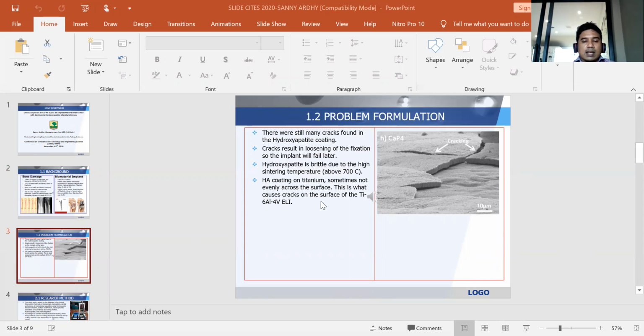Hydroxyapatite coating on titanium is sometimes not even across the surface. This is what causes cracks on the surface of Ti-6Al-4V ELI.